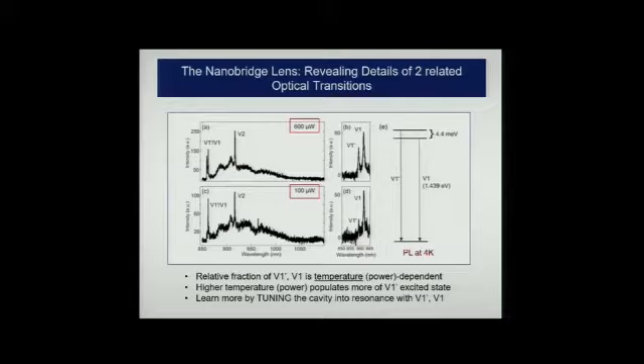Under the conditions of the higher incident laser power, we definitely see that the relative height of V1 prime is higher than under the conditions of lower incident power. Now, why is that interesting? It's interesting because if we look in the literature, other researchers have reported that V1 prime and V1 appear to be related to a transition where the ground state is the same, but the excited state is slightly different. V1 prime has a slightly higher energy excited state than V1.